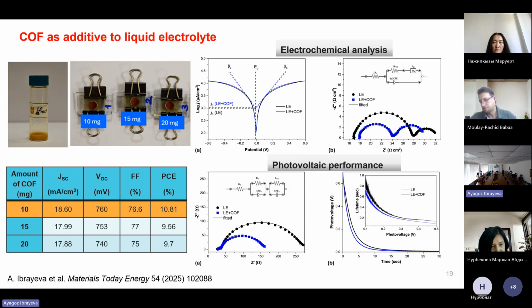Thank you for your valuable question. When we worked on the optimization of these devices, we tried different amounts of this material. And when we increase the amount of this material, it solidifies. In the case of 50 milligrams, it should be in the supporting information of our article, there is the continuation of this table. In the case of 50 milligrams, it is totally solid. Between the two electrodes, there is only solid. And with more solidification, the electron flow was poor and it cannot work. Also for the stability, only in the case of more than 10 milligrams of the amount of this material can it work better. This is our finding.